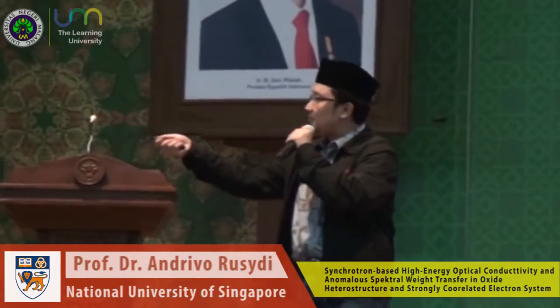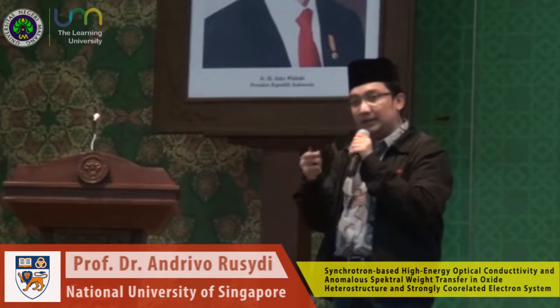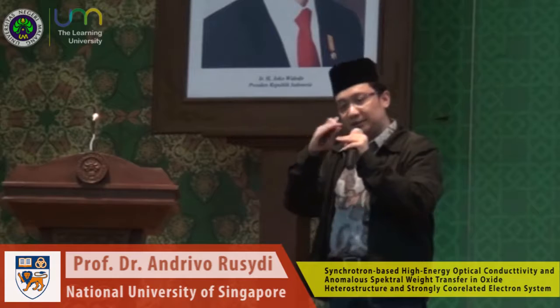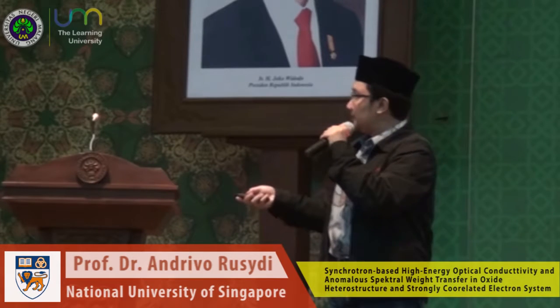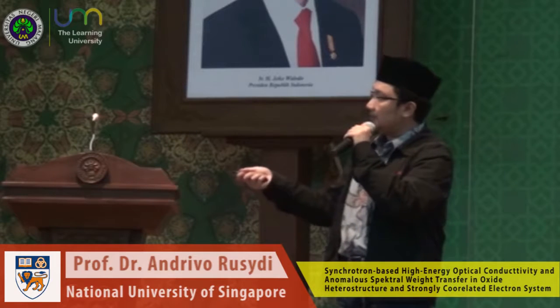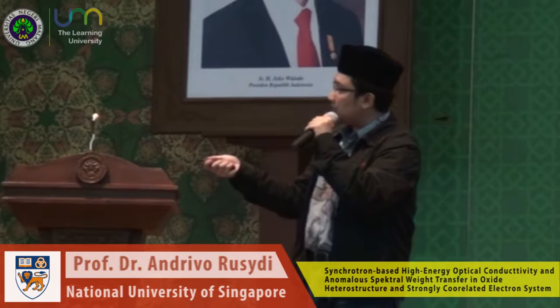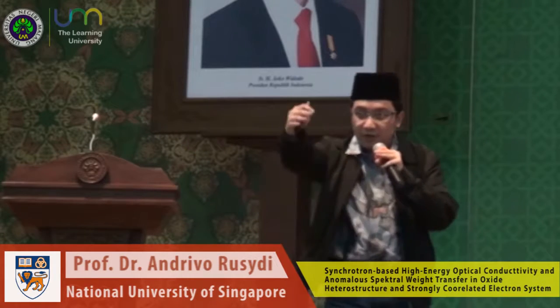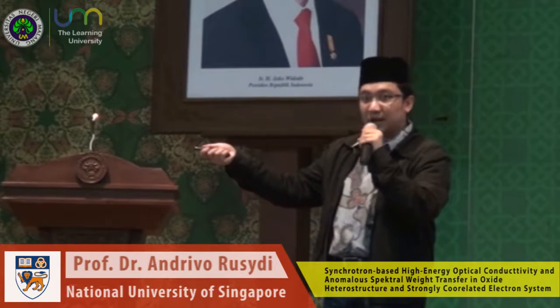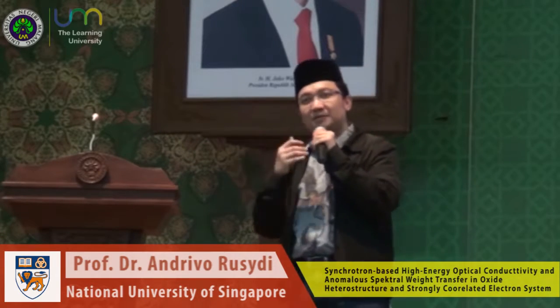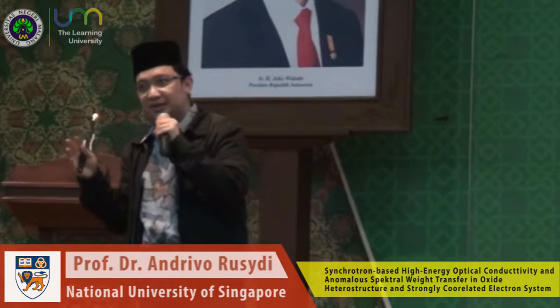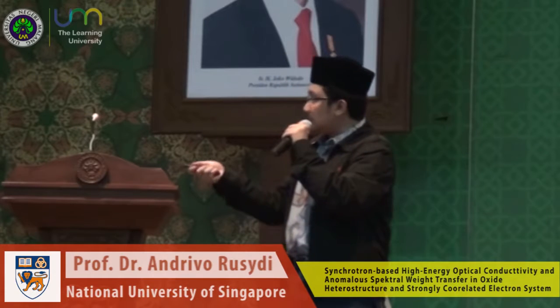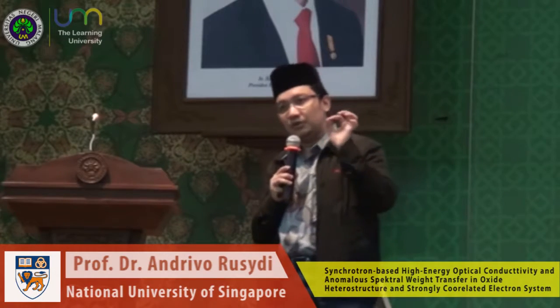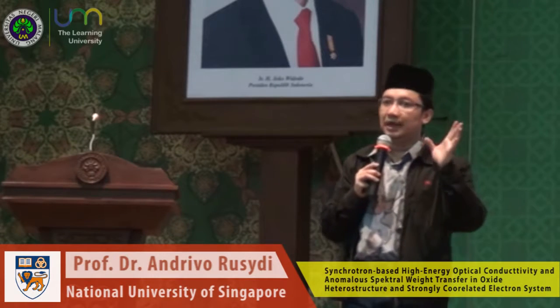Not today. We have the Singapore Synchrotron Light Source, which is really ideal to look at phenomena related to the surface and interface because of the energy ranges. We constructed a completely new beamline. The distance from that corner to that point is about 10 meters, a very long distance with pipes everywhere, so we constructed it from zero. If you like design, you can become a physicist and do art and design, because you can do whatever you like here. The key is that you can tune the photon energy from 1 or 2 electron volts all the way to 1,500 electron volts, so you can scan almost all elements.